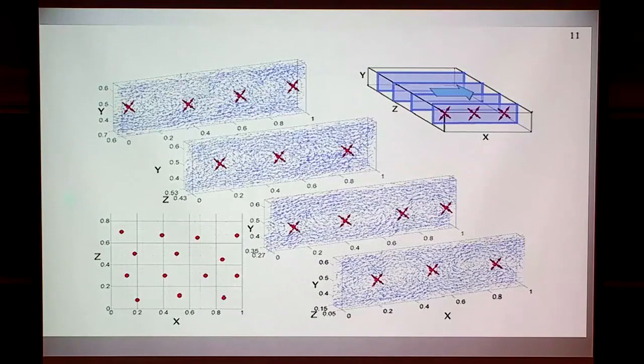My student Kamel Shor, in a heroic numerical effort, actually could see this by looking at careful numerical simulations. He found where these Eshelbys, or these quadrupoles, live along and across a system that is sheared in this way, and indeed they live on a triangular lattice to a very good approximation. So it's a simple generalization, even though the calculation becomes much larger.